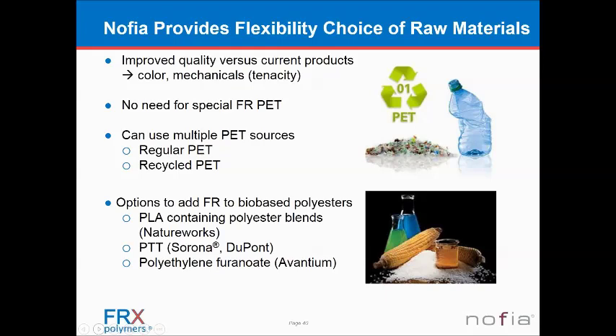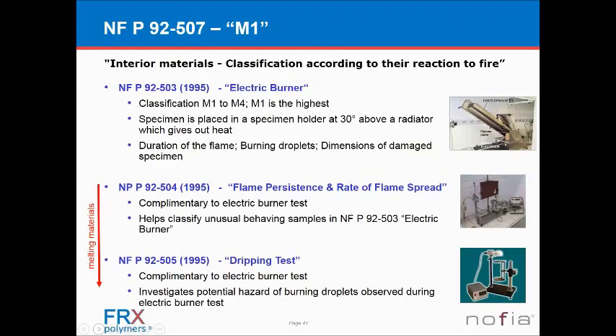And then finally, of course, you can think about bio-based polyesters. You have PLA-containing polyesters, PTT. You have a new material on the market, polyethylene furanoate. These materials are not flame retardant by themselves, and it would be too much to build a flame retardant monomer into the chain. But for these types of materials, you can actually add our material downstream, and that's a big advantage.